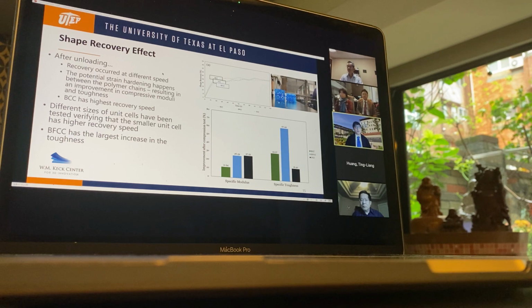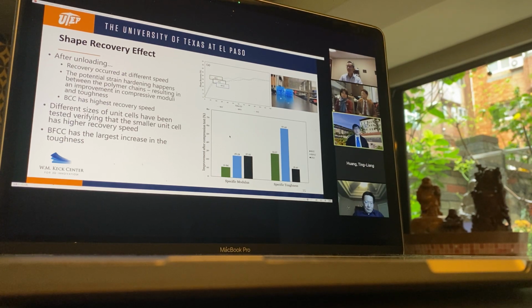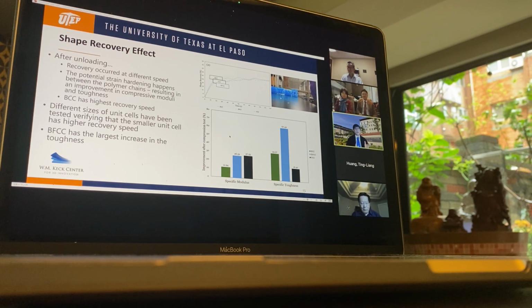That's why we think it's recovering the shape fastest. And about the BFCC, because it is a non-symmetric pattern, which would collapse two layers at the same time, it has the highest degree of deformation. That's why the strain hardening increased the largest ratio of the toughness in the BFCC structure.